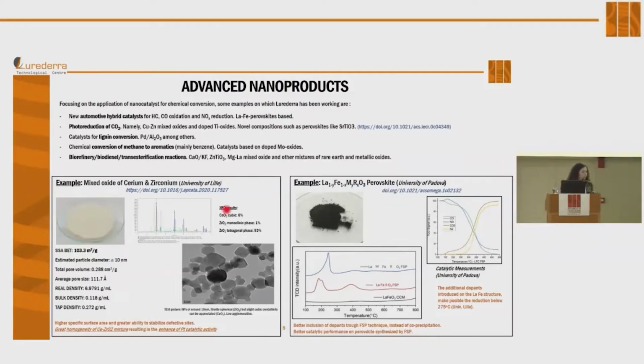Here I have included some interesting examples of two different materials. The first one is a mixed oxide of cerium and zirconium. I have included some images just to let you know how the powder looks, and some characterization, X-ray diffraction and TEM images. The interesting thing about this material was the high surface area, and that we achieved a great homogeneity of the cerium and zirconium mixture, which enhances the catalytic properties. This study was in collaboration with the University of Lille.